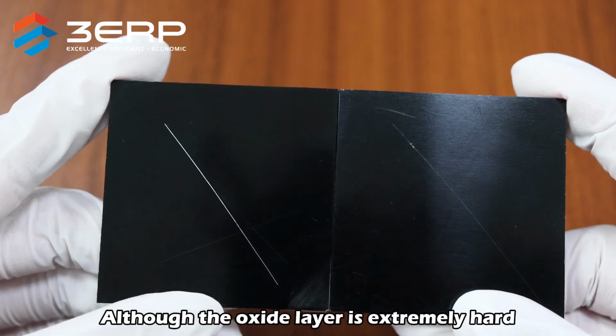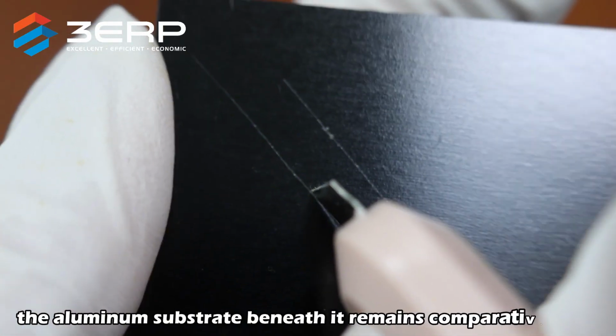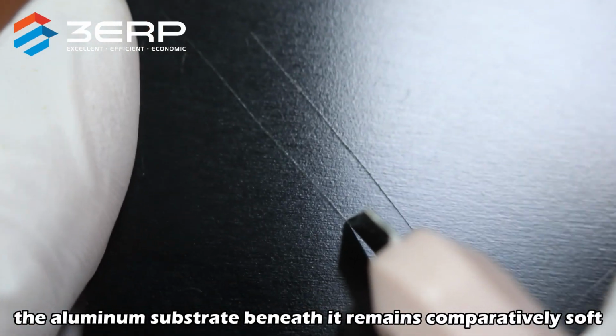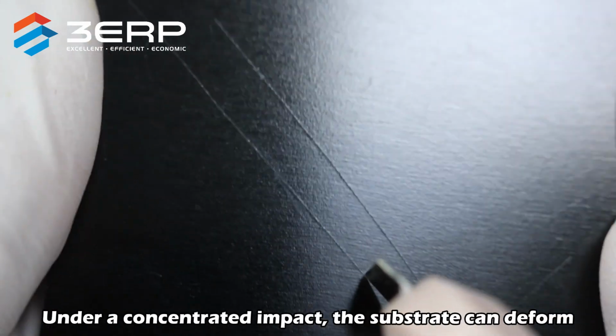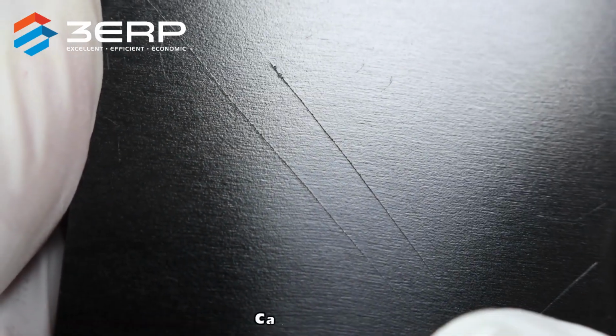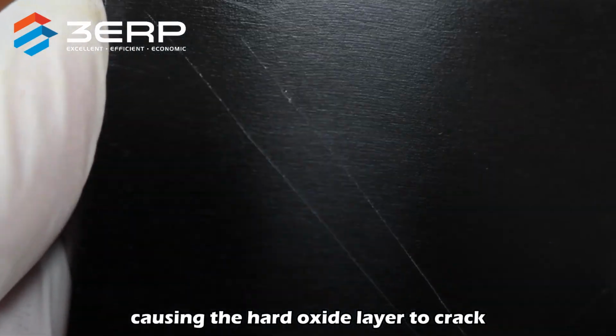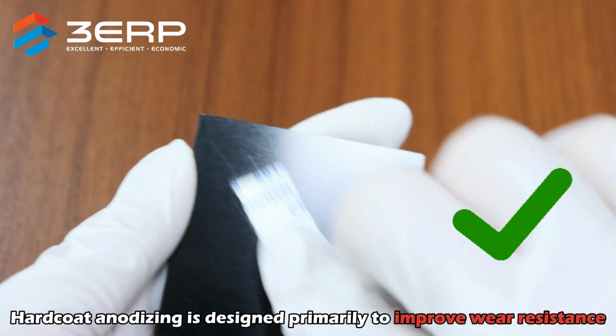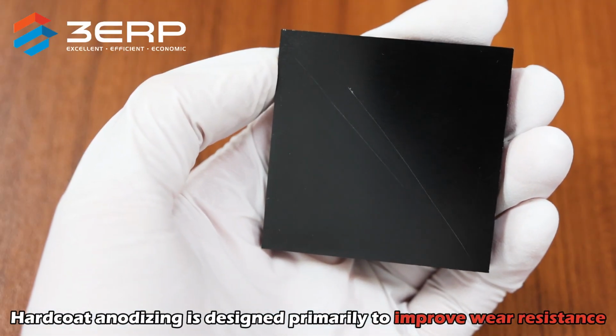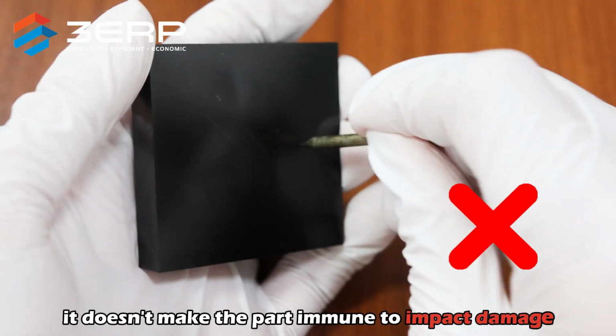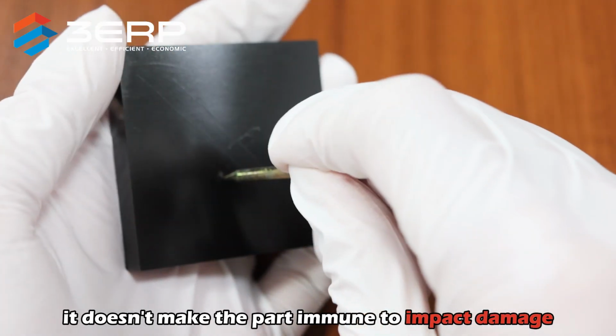Although the oxide layer is extremely hard, the aluminum substrate beneath it remains comparatively soft. Under a concentrated impact, the substrate can deform, causing the hard oxide layer to crack. Hardcoat anodizing is designed primarily to improve wear resistance. It doesn't make the part immune to impact damage.